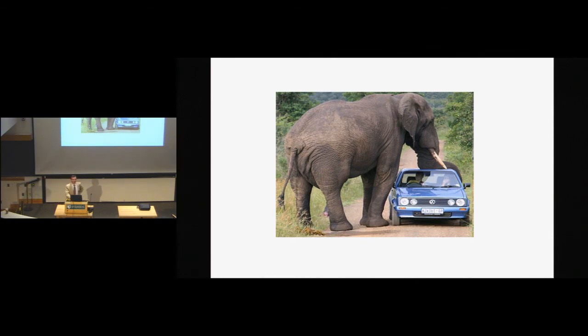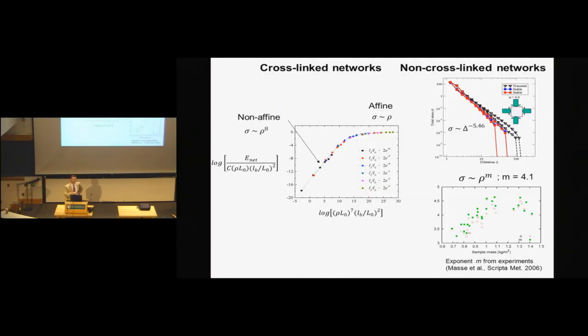All right. So I don't want to get into the details of it, but here is a quick comparison between non-cross-linked and cross-linked networks. On the left-hand side is the plot I showed you before: modulus divided in some, normalized in some way, versus the parameter I used before. You remember the two regimes, the affine regime in which modulus is proportional to density, and the non-affine regime in which modulus is proportional to density to power 8.